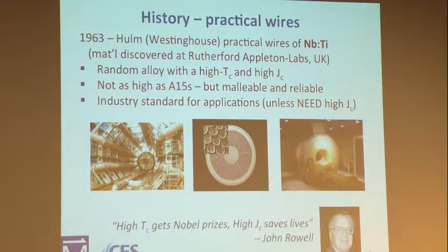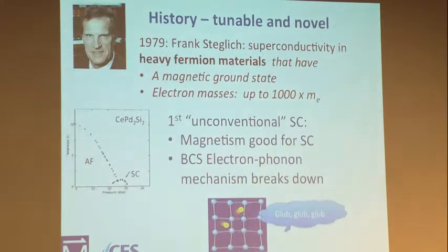It has a lower TC and a lower JC in field than the niobium-3 germanium did or the niobium-3 tin, but it's easier to work with, and this is what people use. And that's what's in your MRI and many things. And when Jack Wernick, my boss, retired, John Rowell said, high TC gets Nobel Prizes, high JC saves lives, which I really don't like that, but anyhow.